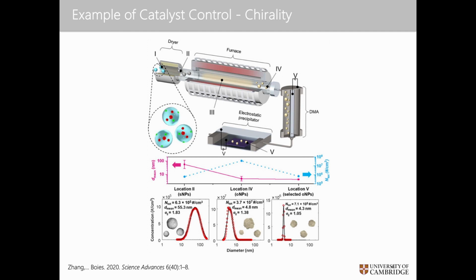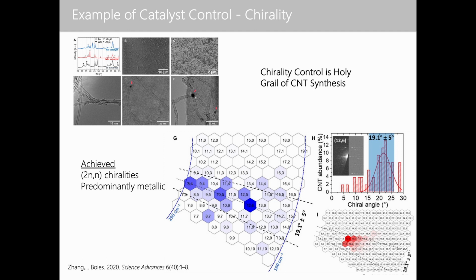The problem is you're throwing away everything else. So by size selecting, the dirty thing is that you're moving a lot of it under the carpet, so to speak. But if one does that, you can do some fantastic things. So one of the holy grails in carbon nanotube synthesis for a long time has been to grow a very precise form of nanotube where one is controlling the chiral angle. So if you think of the chiral angle as you have a sheet of graphene and you can roll that graphene up in any direction, humanity would like to roll that up in a very specific angle, and it would give you very known properties that would be good. And so if you start to control catalysts in this way, you can do that.